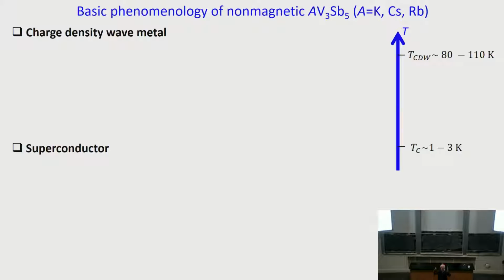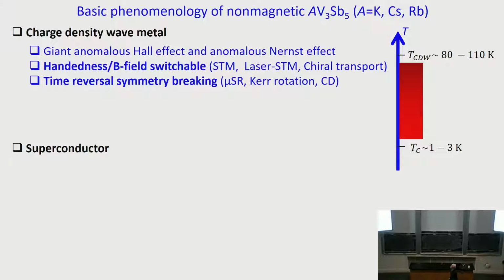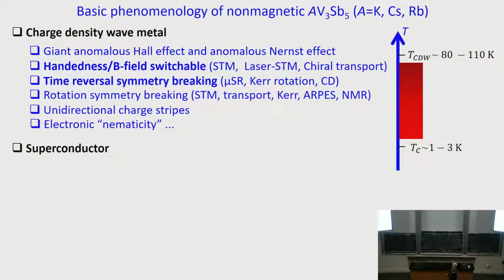Right? It's a CDW superconductor. We can say CDW transition here, superconducting transition here. But it turns out everything in between is anomalous or interesting. First of all, there is giant anomalous Hall effect, anomalous Nernst effect, right? And then the CDW state is seen to exhibit some sort of a handedness, and that can be flipped by magnetic field. I'll explain with detailed experiments. And time reversal symmetry seems to be broken in this charge density wave ordered state.